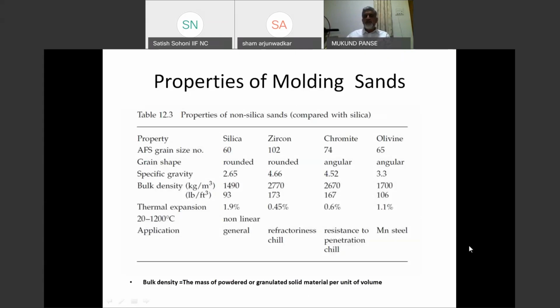You see the thermal expansion of silica sand is more than 4 times that of zircon, 3 times that of chromite, and again the silica sand is non-linear. The refractoriness also is less, but around 1419 to 1500 with application of paint, silica satisfies most of the requirements of sand and can be used effectively.